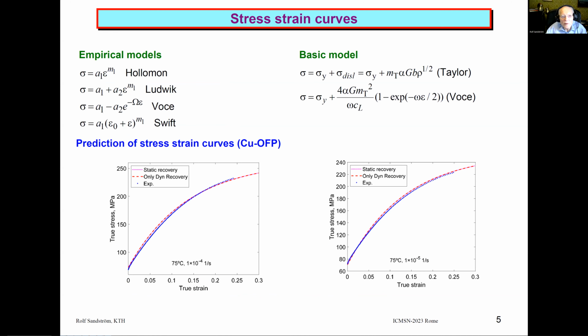The first example is for stress-strain curves. There are a number of empirical models: Hollomon, Ludwik, Voce, Swift, and so on. Only the Voce model is simple to derive from basic principles. You use the relation between the dislocation density and the strength through the Taylor equation. If you apply that in the basic dislocation models, you get more or less directly an expression for the stress-strain curves, which is equivalent to this Voce equation. And that equation works quite well in many cases.